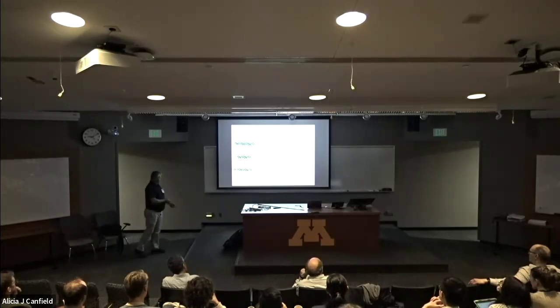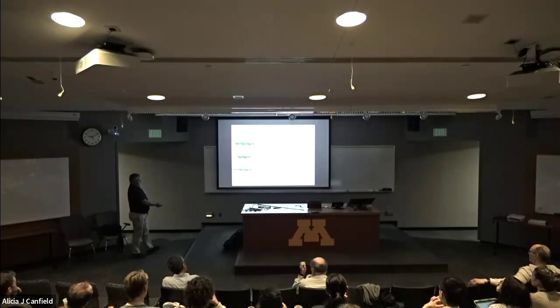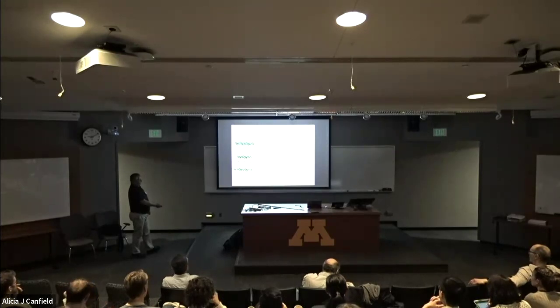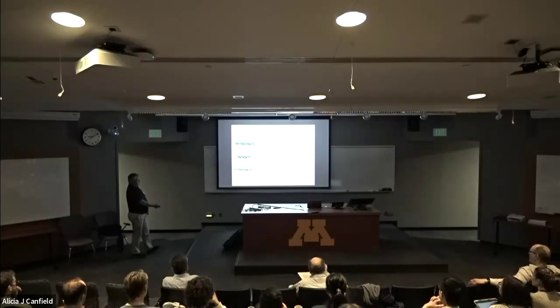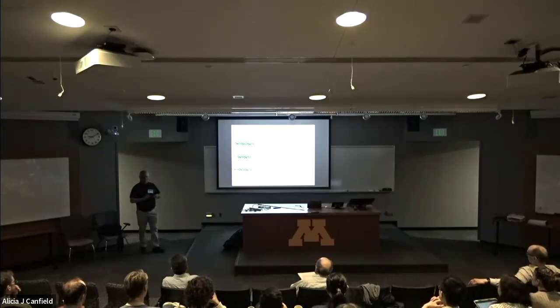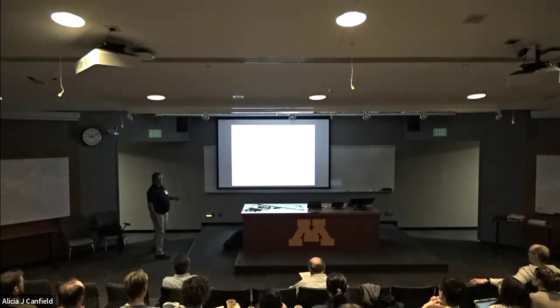And then with the transition metal sites, I'm only going to talk today about cobalt. So the transition metal site is always in the 3+ configuration. For cobalt, that's in the low spin configuration. So the cobalt just gives you a non-magnetic spacer in there. I told you I wasn't going to talk about the chromate or the rhodate. There are a number of papers that will be there as part of the record of the talk if people want to go and read a little bit more about what our group has been doing on those materials.